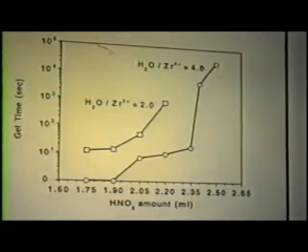Let's take a look at the bottom curve. When we used a molar ratio of four to one, we found out that unless we added nitric acid to the system, we could not even form a gel. What happened is the alkoxide precipitated out of solution immediately. In order to slow down that condensation, what we had to do is to add acid to the system. What the acid does is to protonate the OH group, making the alkoxide less reactive. By varying the acid content, we could vary the gel time by several orders of magnitude.